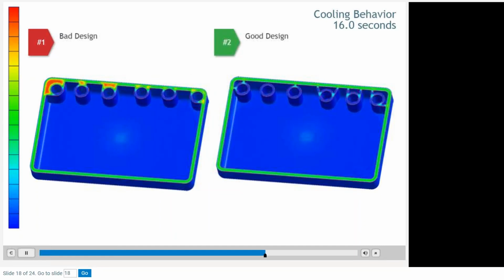At 16 seconds into the packing and cooling phase, the differences become more significant. The temperature in the thicker section in the bad design remains high, while most of the nominal wall thickness for the good design is now at a relatively even temperature. At this interval, you can also see the substantial temperature differences inside some of the bosses on the bad design. These differences will cause significant thermal stress variations, which could lead to cracks and premature part failure.